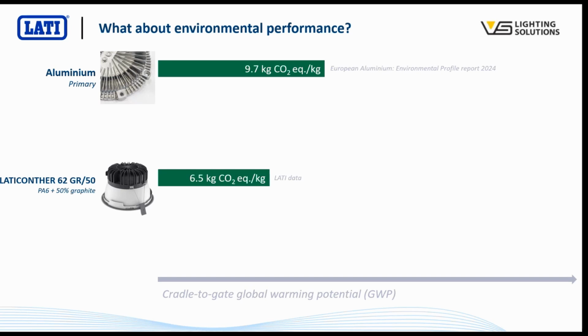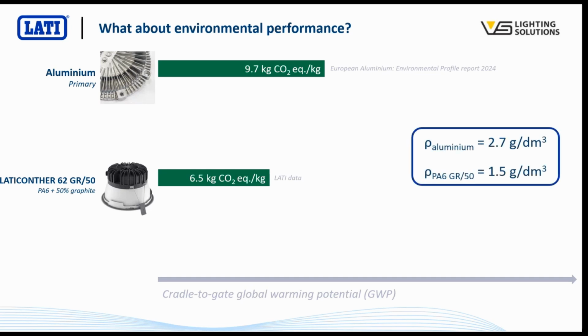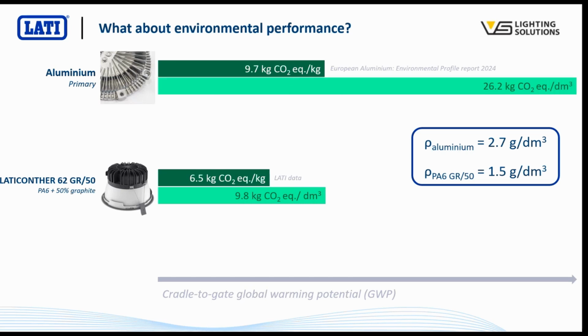But actually, this is not really the right sort of calculation, because if we swap out an aluminium heat sink for a plastic one, those two things aren't going to use the same mass of material, because the density of aluminium is almost twice that of the thermally conductive plastic. So a more accurate comparison is to look at the kilograms of CO2 per unit volume of material. If we do that, we get a figure of around 9.8 kilos of CO2 per cubic decimeter for the LATI Contour 62 GR50. And for the aluminium, we're over 25. So much lower GWP for the plastic version versus primary aluminium.